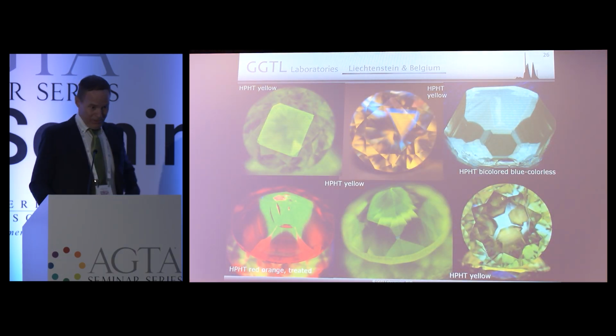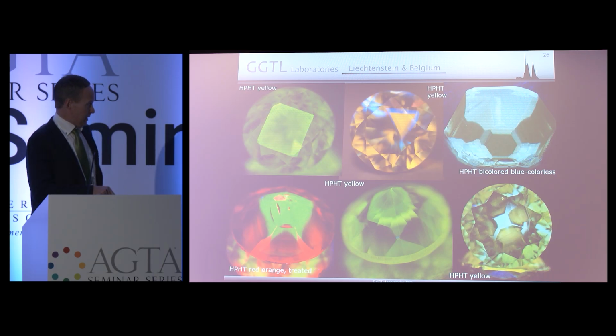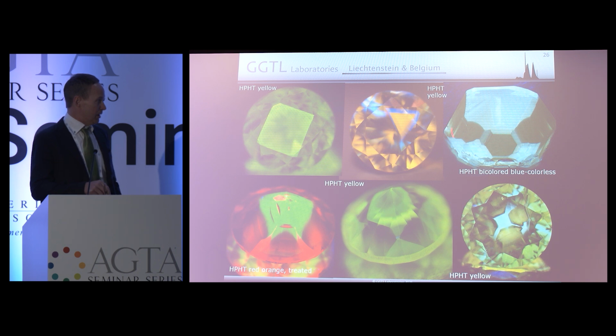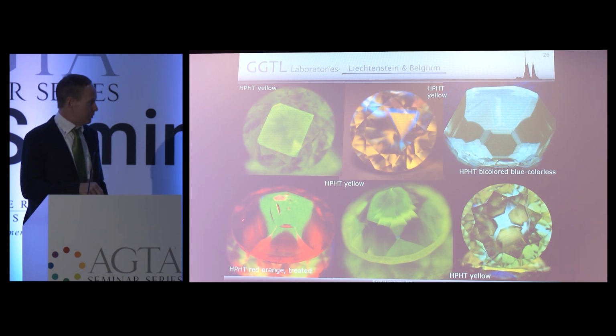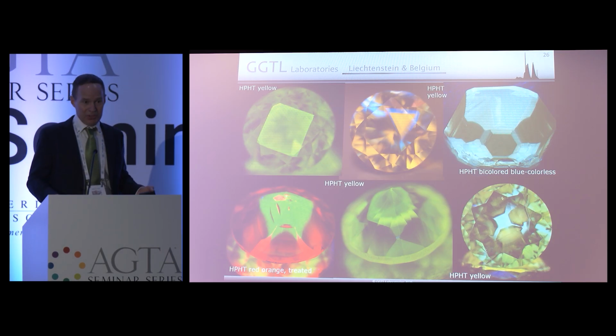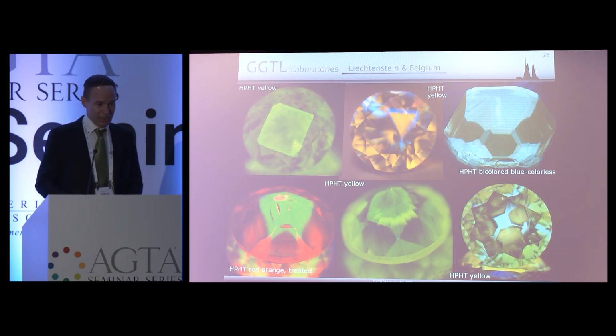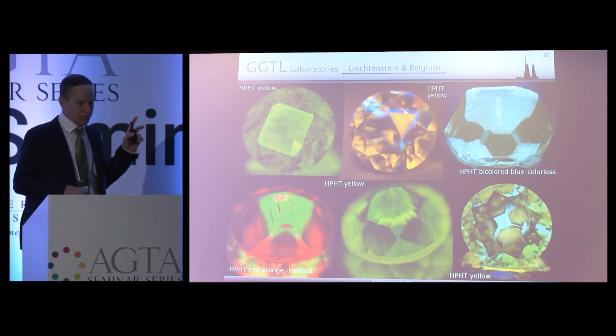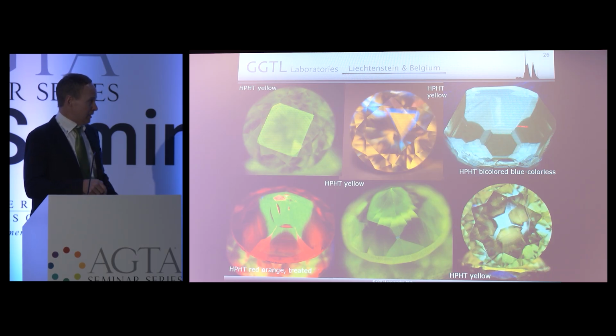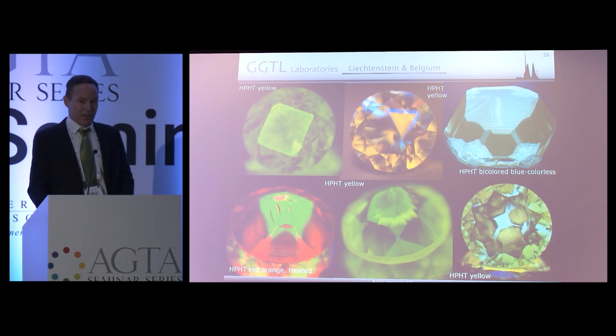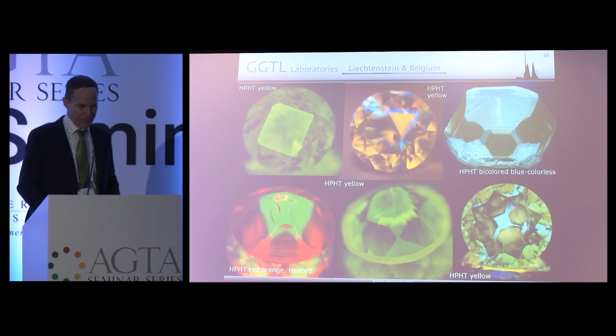Here are a couple of yellows. Yellows to blues. Yellow, blue, no, this is actually a pink because it's been treated, but these are yellows, yellows, yellows. This is a bicolor blue colorless, and this has been yellow, and it's been treated by irradiation and annealing. So that's the kind of patterns you can see. You see already from this image, it's more diverse than what we see in colorless synthetic diamonds. It's even much more diverse than that, because these are the characteristic features that you see. But unfortunately, there's plenty of those stones that don't show those characteristic features. So it's much more complicated than colorless synthetics.